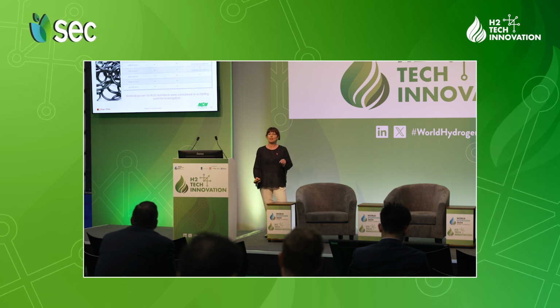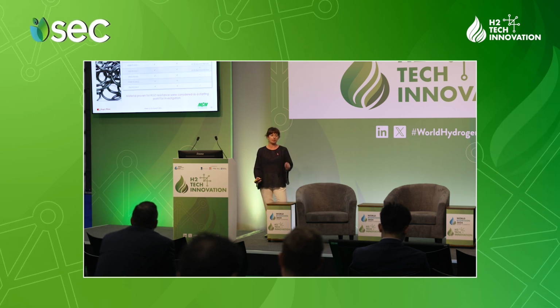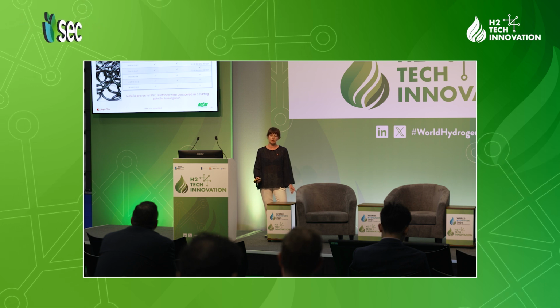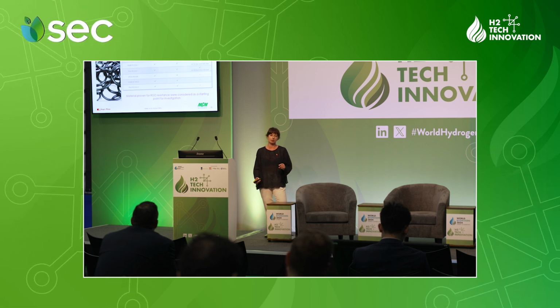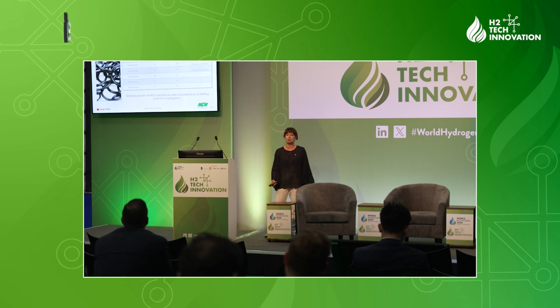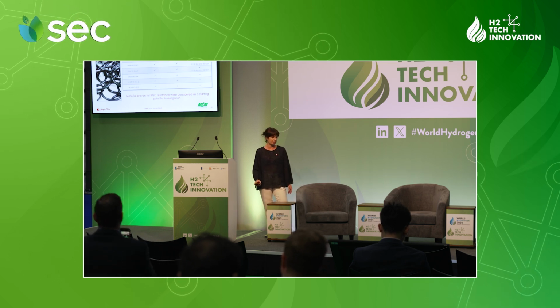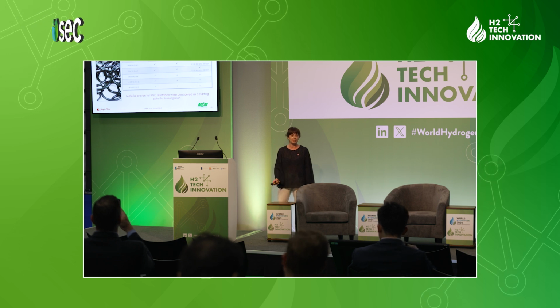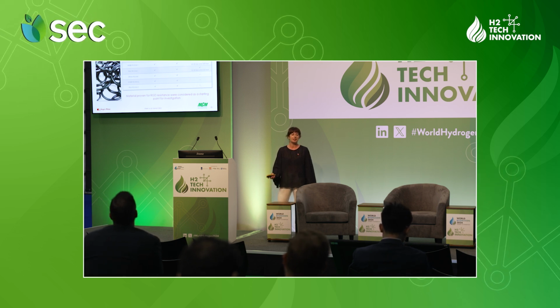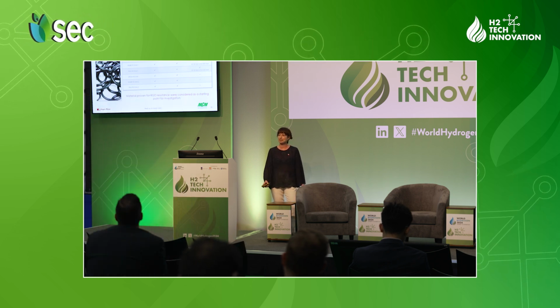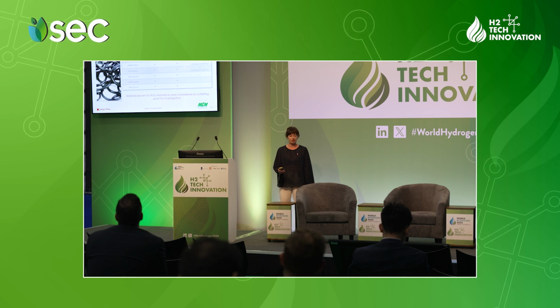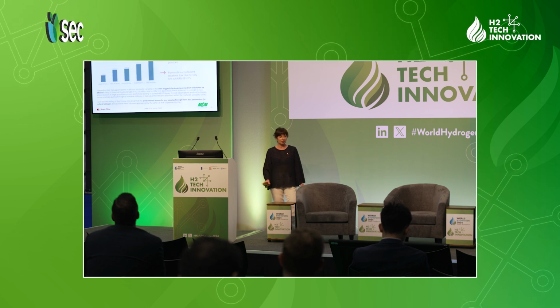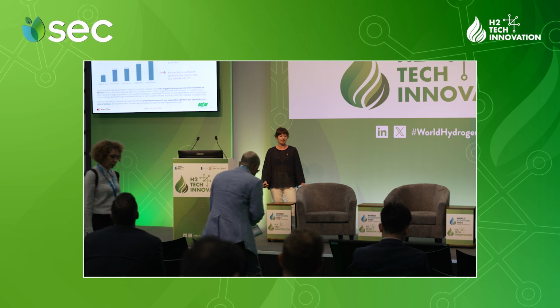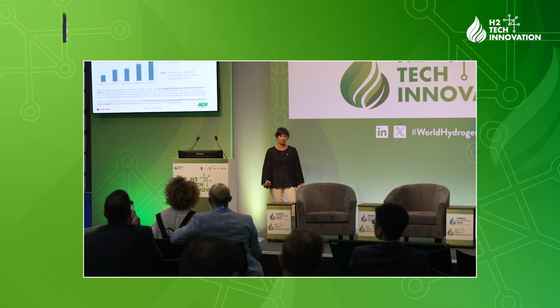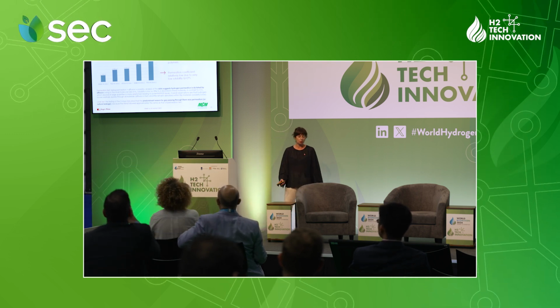As said, we started on 90 Shore compounds. We focused on 2 different HNBR compounds based on 2 different HNBR grades, 2 different FKM compounds, also based on different FKM grades, and 1 EPDM compound. On all of them, we did permeation tests and leak tests in pure hydrogen, 100 degrees C, 150 bar, and on selected materials, we ran rapid gas decompression tests at different pressures. So what you can see here in this slide and in the chart are the results of the permeation coefficient for the different materials that we have worked on.